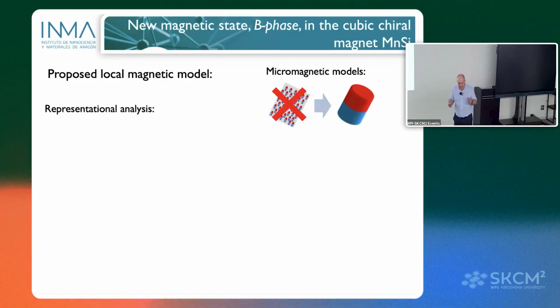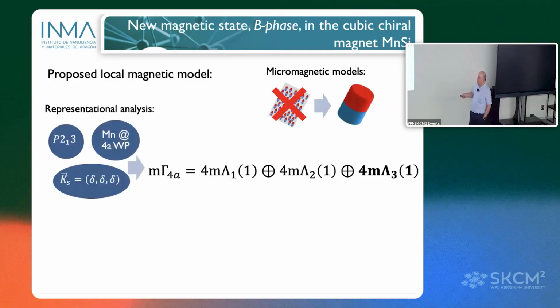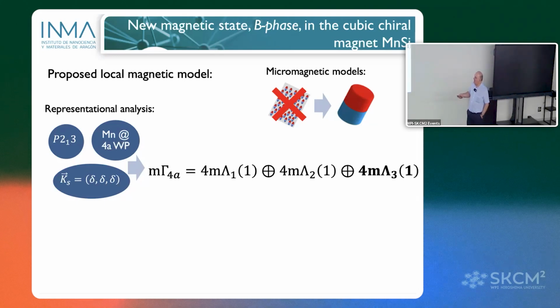Then how to attack this problem? The first thing is to think which are the symmetry-allowed magnetic structures in this compound. We use representational analysis. For this, we need to know the space group, P2_13. The position of the manganese is also along the main diagonals, and the propagation vector is delta, delta, delta, parallel to 1, 1, 1. With this, you can go to the tables, or you can go to BasIreps, or SARAh or another software, or you can do it by hand, and you can determine the magnetic representation and how this magnetic representation for this position is decomposed in irreducible representations. And then your magnetic structure will follow one of these. There are three possibilities.